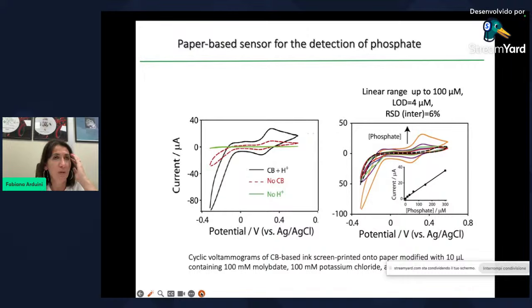So in the paper, we preload the sulfuric acid and the heptamolybdate, and after we dissolve the reagents by adding only the sample. So a few microliters, for example, of river water is able to dissolve the reagents, to have all reagents in the paper-based network, and after we are able to make the measurement.